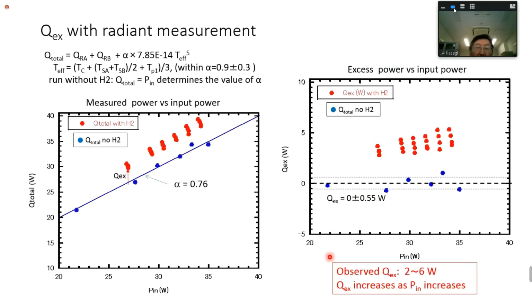Then we can get a calibrated line. So this is the calibrated line, just one parameter finally, alpha. We put the alpha, for example, 0.76, and then the total power, total output is just calibrated by this calibration run. And then you apply this equation for the measurement, you can get the excess heat in this way. So this is the excess heat spectrum, excess heat versus input power. You can observe the excess heat up to 6 watt. The excess heat increases as input increases.